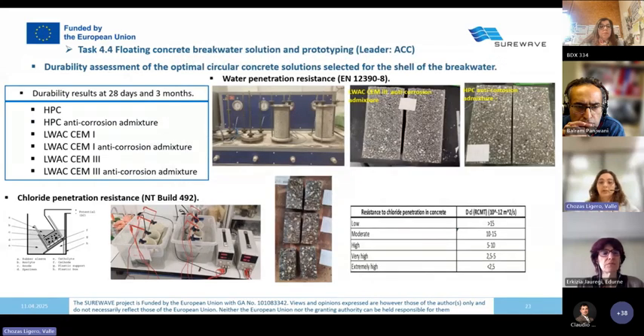With the optimized doses, durability assessment was carried out through water penetration resistance tests and chloride penetration resistance. The dosages analyzed were high performance with anti-corrosion admixture, lightweight aggregate concrete with cement type 1 and with anti-corrosion admixture, and with cement type 3 and with anti-corrosion admixture.